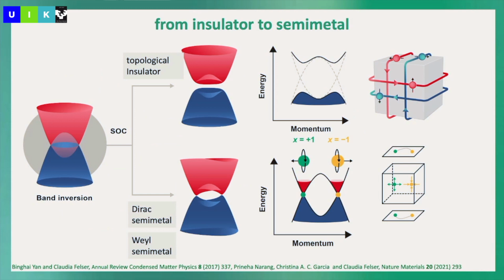Okay, so going back here again, we have this overlap between the conduction and the valence band, and then we have this overlapping region. If we draw this all in 3-dimensional, now we become more complex. Charlie did 1 and 2-dimensional. If we go to 3-dimensional, we have not only these crossing points, we have even an overlapping area, and very often you have these nodal line compounds, which also show very interesting properties. And if this whole area is forbidden, we can have the topological insulator with a nice surface state.